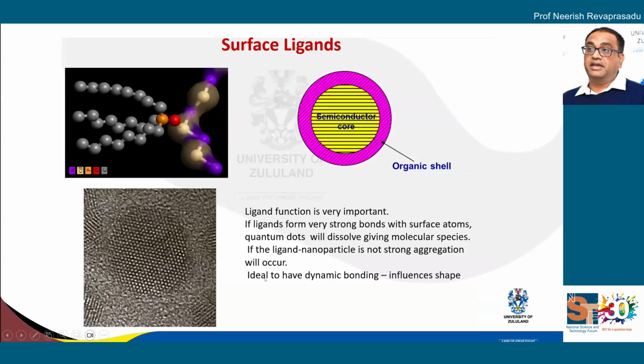So again, just a brief slide on surface ligands. As I said, you need to not have any defects because you want emission at the band edge, and you normally use organic shells that will make sure that they passivate the surface, and more importantly also prevent any aggregation. So this is an example of a quantum dot, 4 to 5 nanometers, maybe about 3,000 atoms, and passivated. You can't see the halo, but around the dot there is an organic shell.